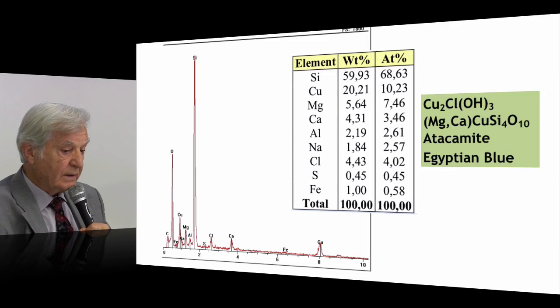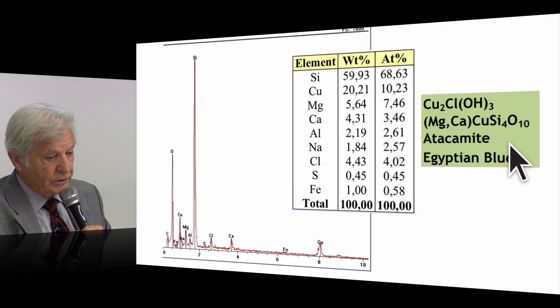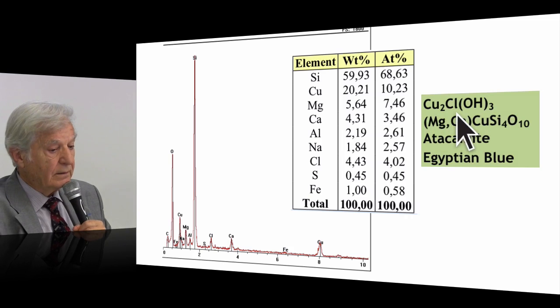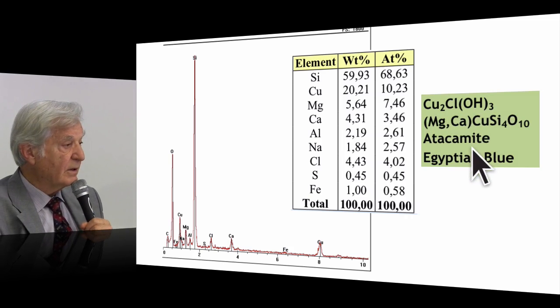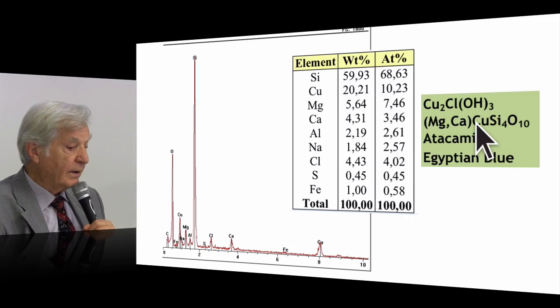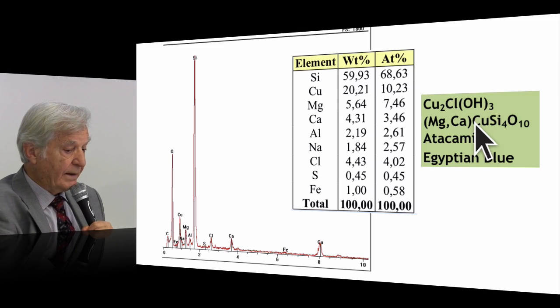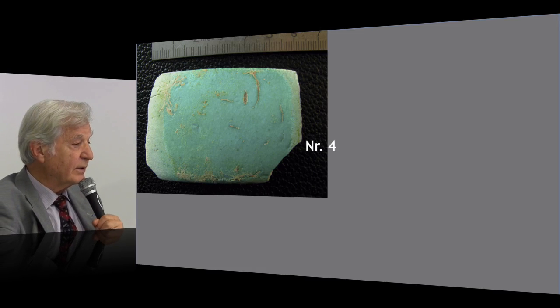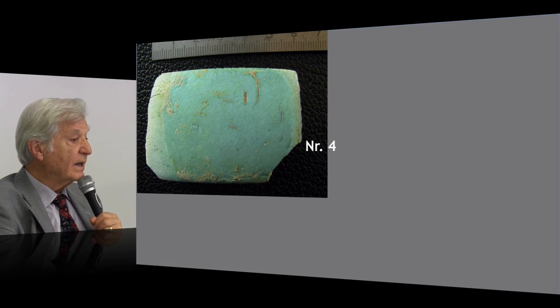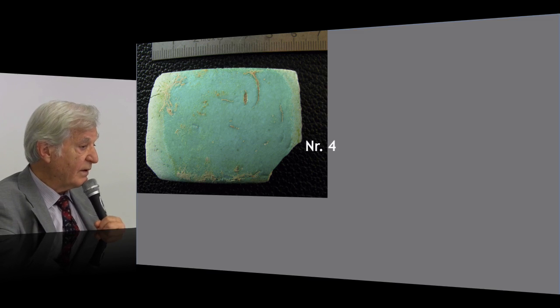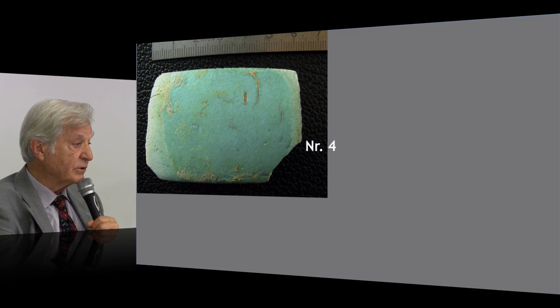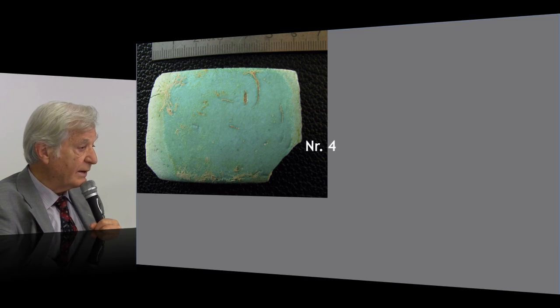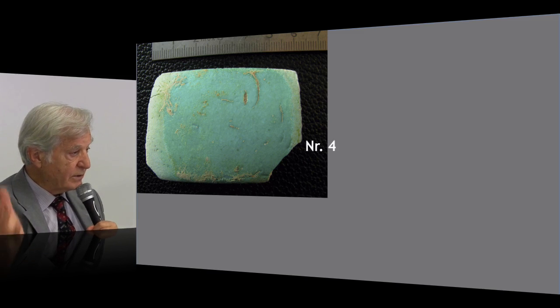We suspected that we were dealing with a material based on copper chloride, that is the atacamite, famous also in painting. This is a pigment. And we started to look at the tiles. It is a hydrate that does not exist if it is fired at 800 degrees C. It is totally destroyed. It is turned into copper oxide. It cannot be there. So we selected several tiles.